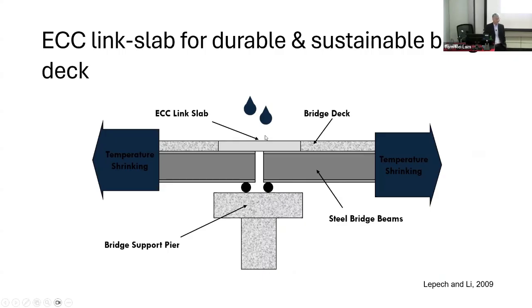This was the very first test of ECC in the field, and it was carried out in collaboration with the Michigan Department of Transportation, MDOT. They expressed to us that they experienced problems in both performance and cost because of the failure of the expansion joints on bridge decks. And they need to repair those joints every summer, which was expensive for them. So they wanted a more permanent solution. And what we suggested is to remove the steel expansion joint, remove some portion of the adjacent concrete slab, and replace the whole thing with an ECC link slab.